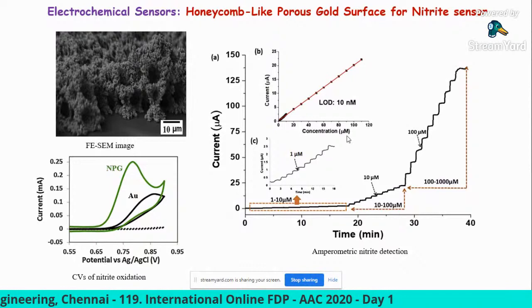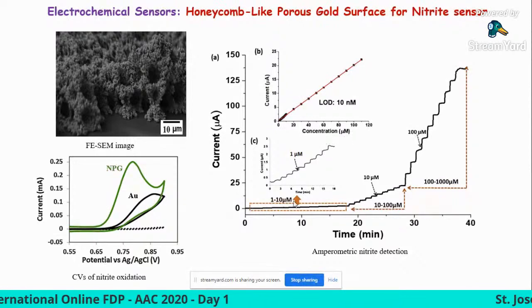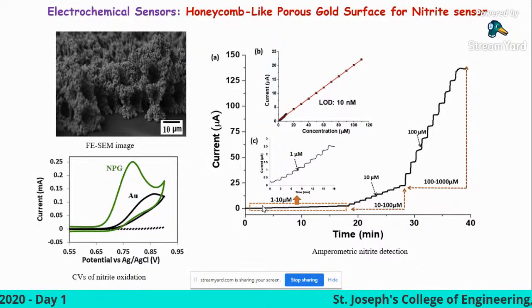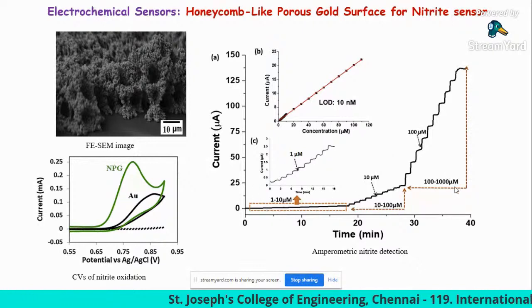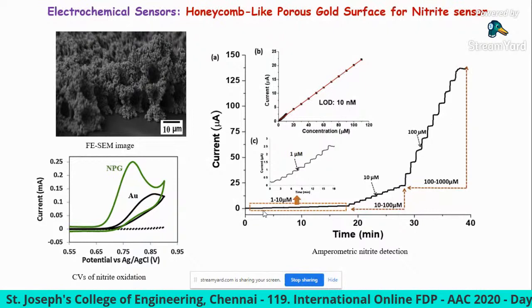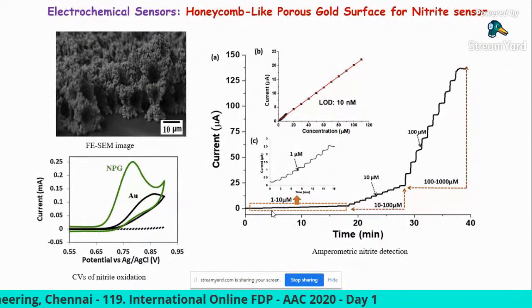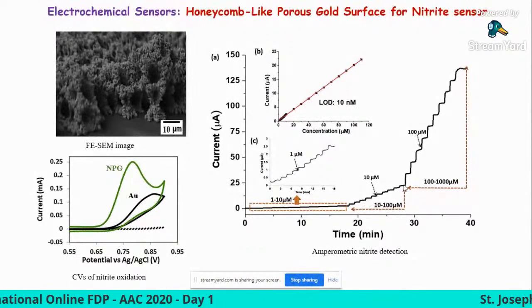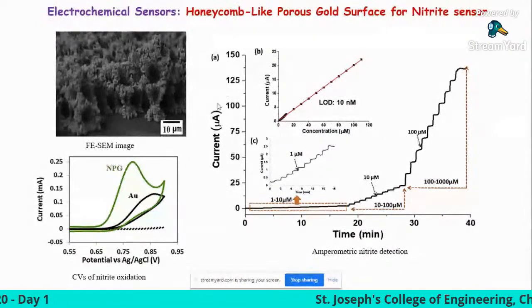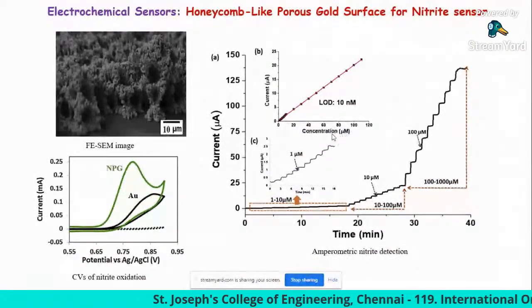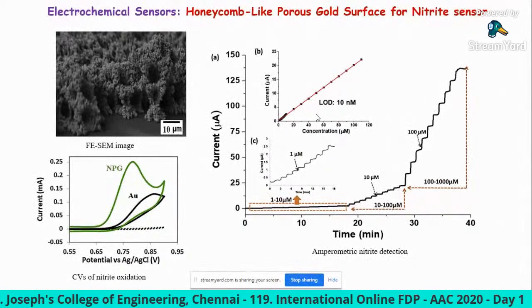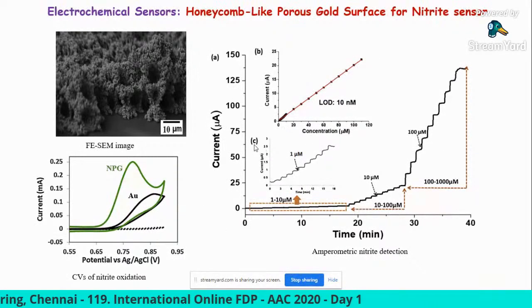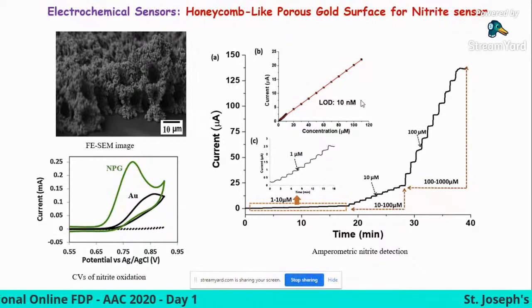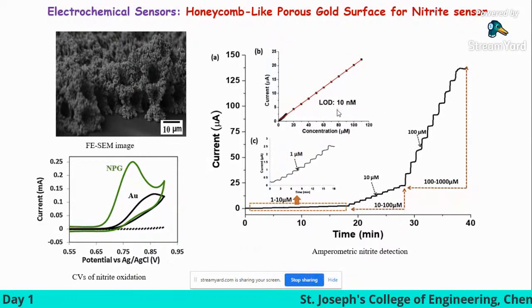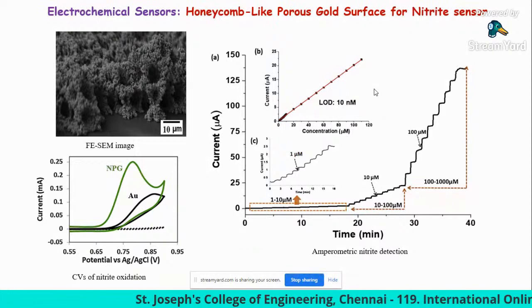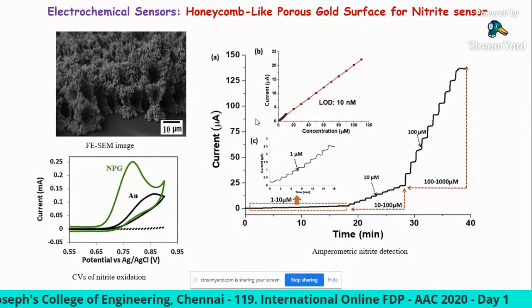So this is the amperometric response for nitrite detection. We started from 1 micromolar to 1000 micromolar, a very long linear range. Whenever we add the nitrite, the electrode responded well and the current signal increases. If you plot the current versus the nitrite concentration, it shows very high linearity. Using this method, we can achieve a limit of detection of 10 nanomolar, which is very, very low compared to the normal level. So one can use this material as a sensor for nitrite.